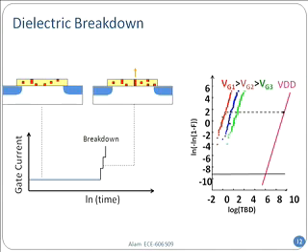It's called a Weibull distribution. So evaluate the function and put a dot there. And you keep putting the dots. And that creates this straight line, the red straight line. Similarly, if you reduce the voltage a little bit, then you can get the blue one. Why? Because if you reduce the voltage, defects will form a little slower, and so it will take a little bit more time for the bonds to break, and as a result, it's shifted a little bit to the right. By the way, where I draw a dotted line, that's sort of where the 50% point is.